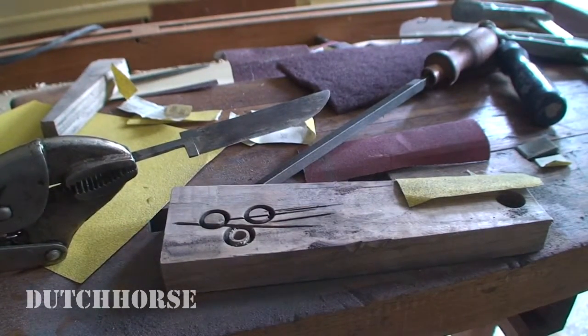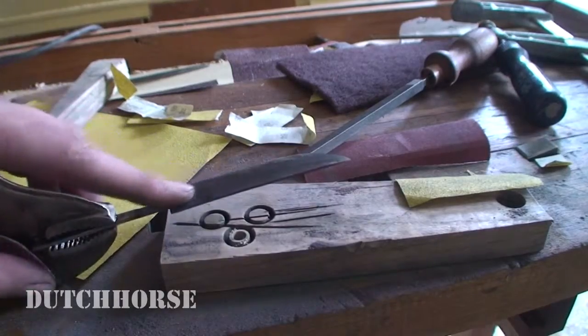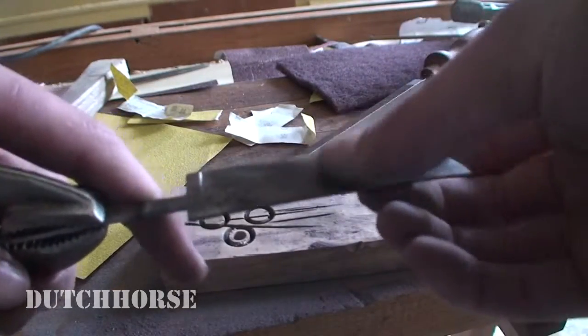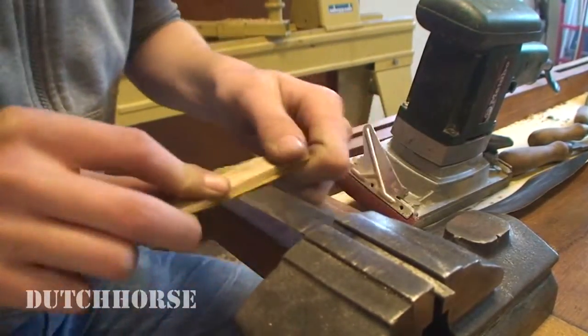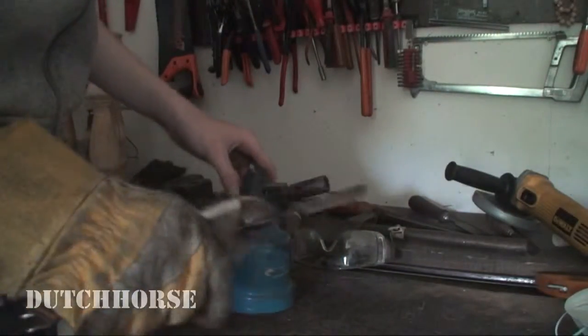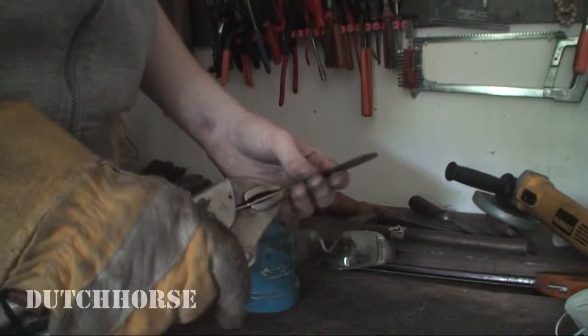So that means hardening went well. The next step is tempering the blade, which allows it to become a little less hard. But before I do that I need to polish it up a little bit so I can see the tempering colors on the blade. As far as tempering goes, I am going to heat this blade up until it's some sort of golden straw color and then quench in the water again.